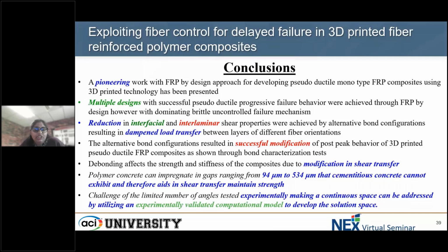Alternative bond configurations have been successfully modified using 3D printing technologies, and that has also been shown to successfully demonstrate some pseudo-ductility and behavior with high ductility indices. Debonding affects the strength and stiffness due to the modification in shear transfer. So that's what goes back to what we were saying as to there needs to be that optimal kind of debonding that still doesn't affect the shear transfer, but also gives us that progressive kind of delayed failure.